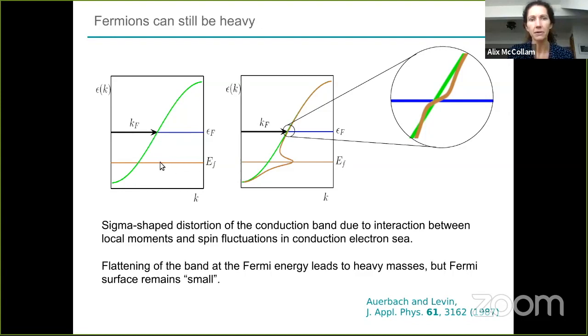The F levels sit here, some distance quite close. This is typically only a few hundred millirydbergs or some small distance from the Fermi energy. In this case, there's a resonance here, or a distortion, at the F level, and this gives you a distortion at least at the Fermi energy.